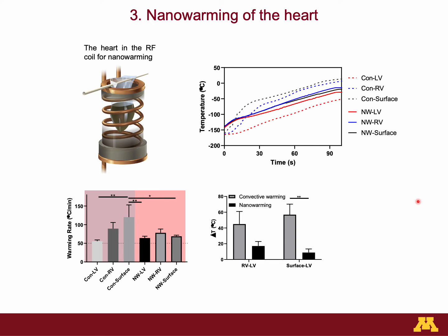After the vitrification, rewarming of the heart was performed. We compared the physical characteristics of convectively warmed and nano-warmed hearts. To assess convective warming, VS55 loaded hearts were placed in the same cryobags with the same volume of surrounding CPA solution as the nano-warmed hearts, but without silica-coated iron oxide nanoparticles. Then we cooled to the vitrified state according to the same cooling protocol. The convective warming was conducted in a 37 degree water bath, and nano-warming was performed in a 15 kilowatt radiofrequency coil at 185 kHz, as shown on this slide.